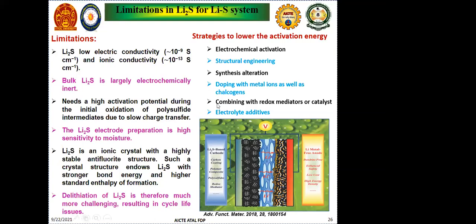And the other ways are that we can also use redox mediators or catalysts with the Li2S, so that its conductivity will be increased, as well as activation energy reduced. Apart from the electrode, we can also develop the electrolyte in this Li2S system. Usually in Li2S we use LPS as electrolyte. So in this LPS system we can add some additives, or we can coat the PEO or other polymer on the electrode to improve the performance.